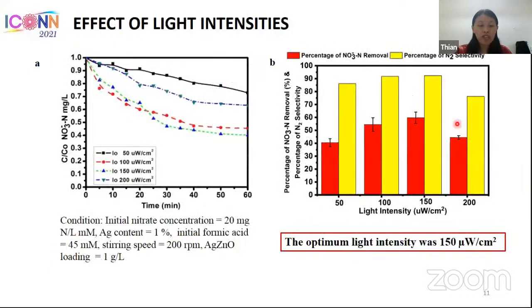And finally, this is the last parameter that we study here. It is the effect of light intensity. If we increase the light intensity, as you can see here, from 50 to 150 microwatts per square centimeter, there is an increase in percentage of removal up to 60%, but beyond that, it is reducing at 200 microwatt per square centimeter. Too high a light intensity results in electron-hole